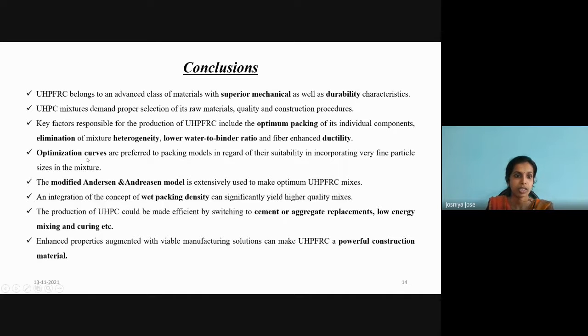Considering the design approaches, optimization curves are preferred to packing models due to their ability in incorporating very fine particle sizes in the mixture, out of which a modified Andreasen and Andersen model is being extensively used to make optimum UHPFRC mixes. And it is suggested that the concept of wet packing density, along with the modified Andreasen and Andersen model, can significantly yield higher quality mixes. Nevertheless, sustainability should be considered. So, cement or aggregate replacements or low energy mixing and standard water curing could be adopted. And if all these manufacturing methods could be implemented, then UHPFRC definitely serves to be a powerful construction material.